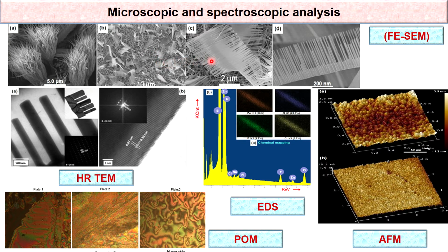And it shows that the nanocomb consists of nanorod-like branches, which we call teeth, and a long ribbon-like stem. And these are the HRTEM images and the selected area diffraction pattern. They are used for determining the crystalline nature, size and shape of the synthesized zinc oxide nanocomb. These images were critically analyzed to describe the atomic structure, and the figure demonstrates that the nanocomb teeth are associated along one side of the ribbon-like stem. The HRTEM image and the diffraction pattern of a branch of the nanocomb are indicated here, and it provides an important study of the crystal structure of the zinc oxide nanocomb.